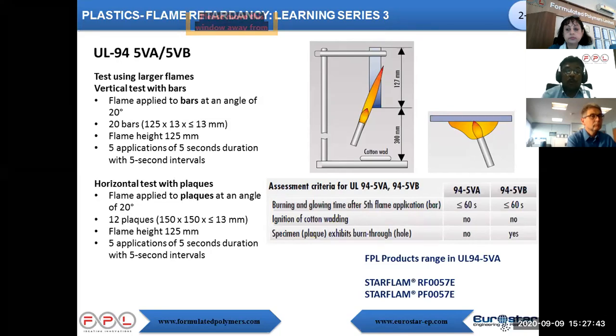For the 5VA, 5VB test, the gas flow rate varies to maintain a flame height of 125 mm, and the inside blue tip should be 40 mm. The test procedure: apply flame for 5 seconds, remove and wait for 5 seconds. Again, repeat the same 5 times. Acceptance criteria: total flame time of 5 attempts should not exceed 60 seconds. No debris should be found in the cotton bed underneath. No hole formation should occur for 5VA classification, but hole formation is accepted in the case of 5VB classification.